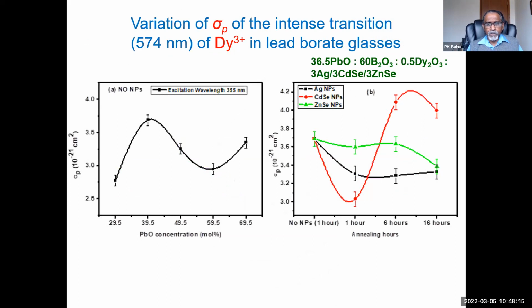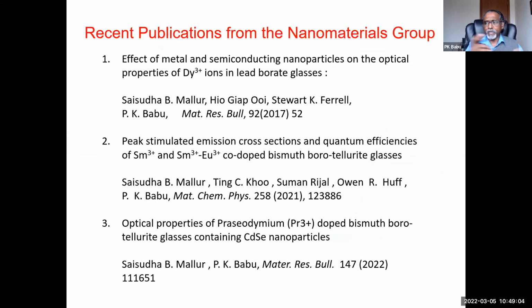Just by analyzing this emission spectrum, we were in fact able to determine the average size of the cadmium selenide nanoparticle. Again, this is one particular work where we incorporated some cadmium selenide and zinc selenide nanoparticles into a glass containing dysprosium, that was the lanthanide ion, and we tried to look at the efficiency of the fluorescence transition. It is measured by a parameter known as stimulated emission cross-section. You can see that there is significant improvement in the stimulated emission cross-section when you have nanoparticles of a particular size present in that. This is a big jump in the efficiency of the fluorescence emission from these particles. Just a list of some of the recent publications where we have used nanoparticles for improving the fluorescence emission of lanthanide ions. Just to give you a small flavor of the work that we do in our lab.